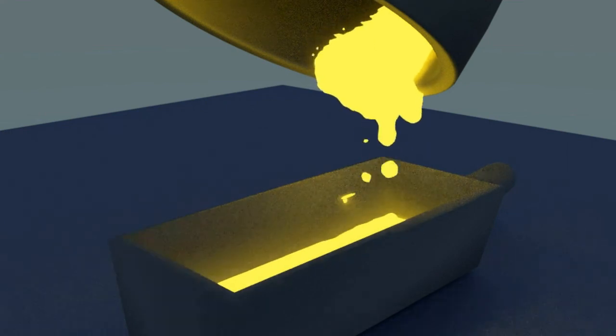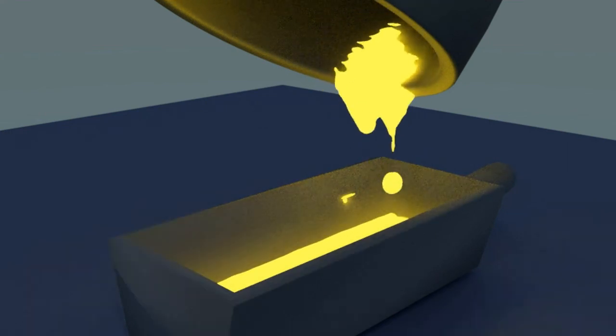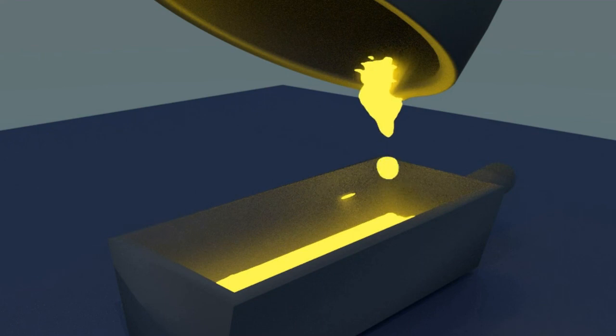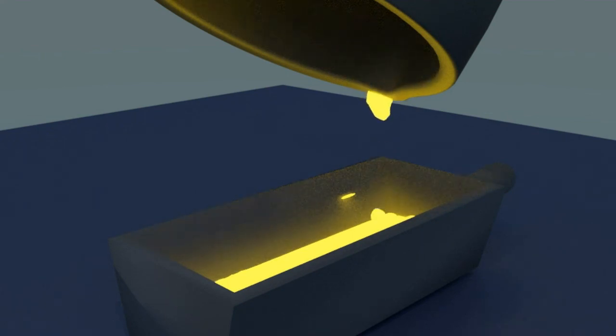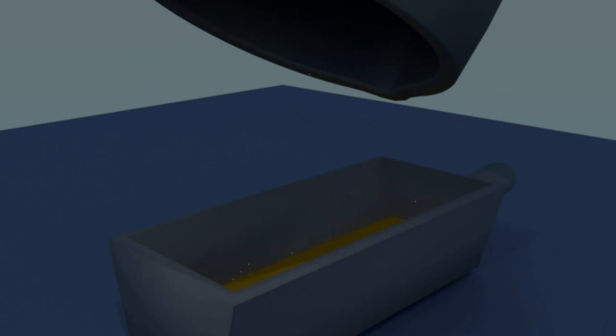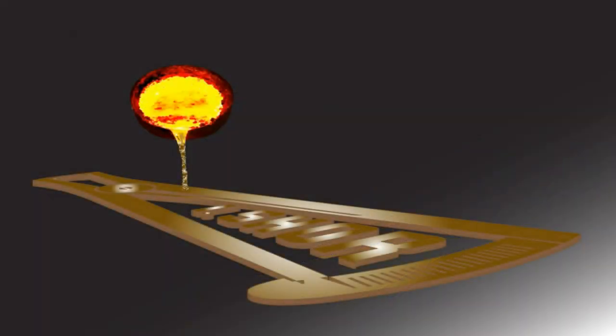Melting. If you are not familiar with melting gold, it's probably preferable to have a jeweler melt it for you. However, if you choose to do your own melting, please note the following. Use either a new crucible, or one that has only been used for melting pure gold. Use of any other crucible will contaminate your gold. Flux your crucible before using, to seal the crucible's pores.